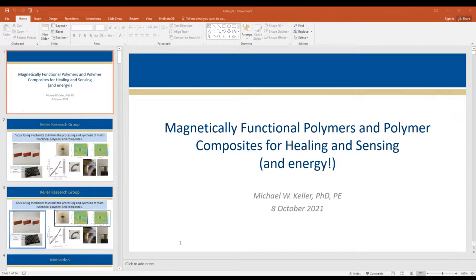And actually, we had to cut off down here at like 0.02% because we couldn't physically measure the microcapsules efficiently anymore. There just weren't quite enough of them. And so what you see, right, when you look at the fracture surface in SEM is this is the statistical mix, and you see just a few capsules, but then when you concentrate them, shockingly, there's a bunch of them right there. So this was just a fun toy that we were demonstrating that we could do. The actual idea had initially been to complete the next work, and we'll look at that.